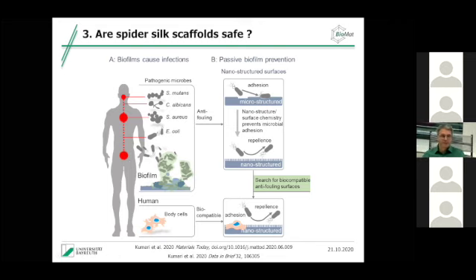And typically this is done with antibiotics. But as mentioned, some Staphylococcus aureus are already resistant to most commonly used antibiotics. And also you cannot give antibiotics forever, right? So what you will actually need is a microbe repellent scaffold material. That would be the best. And you can do that by structuring surfaces. Nanostructuring of surfaces has already been shown to be microbe repellent in comparison to microstructured surfaces, because those are actually well suited for bacterial adhesion. So nanostructuring is the key, but nanostructuring will also repel, again, all the human cells. So we are again in the problem.